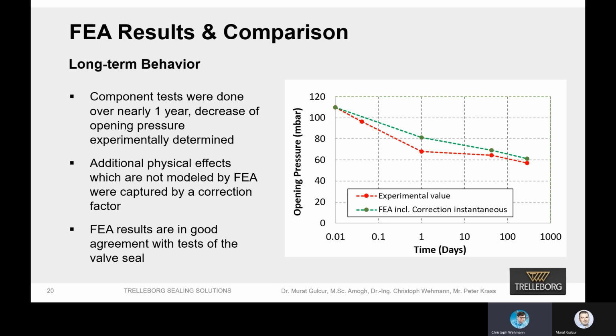And to make sure it's describing the long time period of 20 years, we did this test at an elevated temperature too. So it's not the application temperature, so it's elevated so that we in the end consider nearly 20 years when we break it down with Arrhenius to room temperature. So, and you see, we can simulate this here quite accurately. So we are sure that we can predict the lifetime, in this case, the opening pressure of our seal or valve in an accurate way.